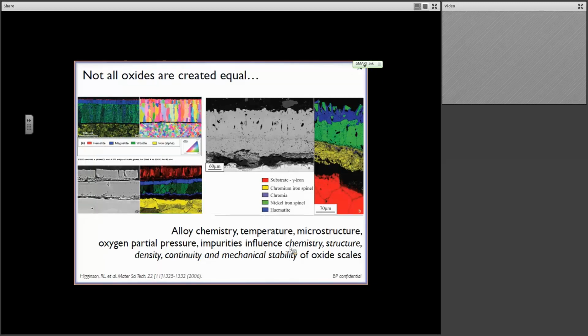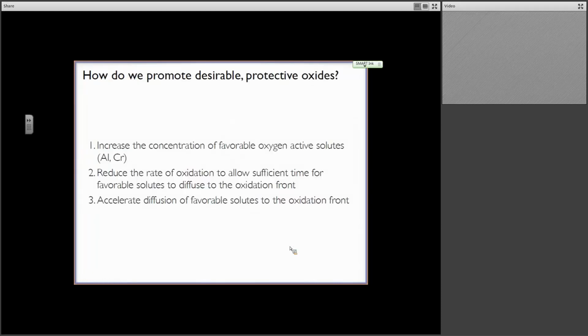So again, we go back to our question of how do we understand this? How do we create a passivating scale on what would otherwise not form a good passivating scale? Now, in order to think about this, we turn to the literature, and we can see that in most cases we have some guidelines as to how to create and promote desirable protective oxides. The first thing that we think of is to naturally increase the concentration of favorable oxygen-active solutes. Like chromium, we put chromium into stainless steel, we improve the corrosion resistance, right? Aluminum is also a highly desirable oxide former because it's mechanically robust.